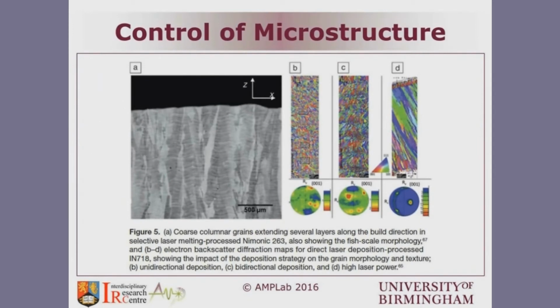Now, where is the future heading in additive manufacturing of nickel superalloys? One thing many studies have shown, and it's on the cover of the MRS Bulletin issue, is that one of the flexibilities in additive manufacturing is that we can control the microstructure. If you look at the typical microstructure from additive manufacturing, we end up having columnar grains in some cases, extending from the bottom to the top of the build.